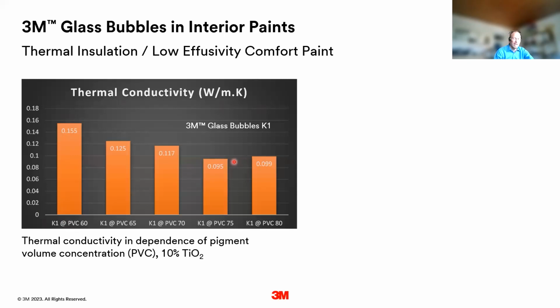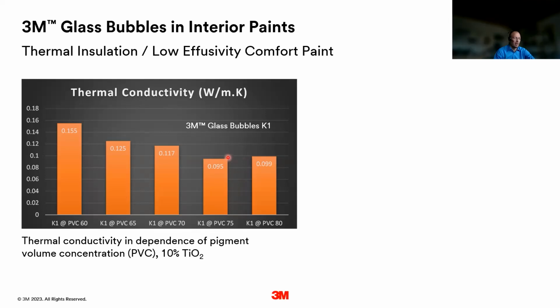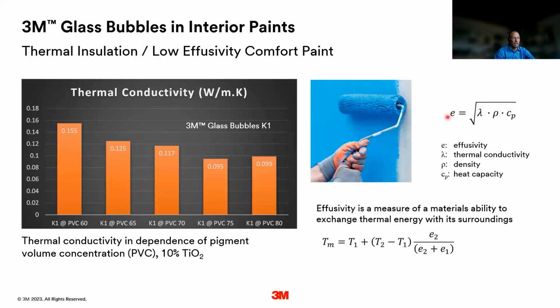And of course, paint that is applied only in very thin layers is not replacing the insulation of a house. It's by far too thin, but it can provide some benefits, such as higher wall temperatures, and also something we call low effusivity. Effusivity, actually, that is a little formula, which is the square root of thermal conductivity multiplied with density and the heat capacity. And actually, this is the value that defines if a material feels warm or cool.